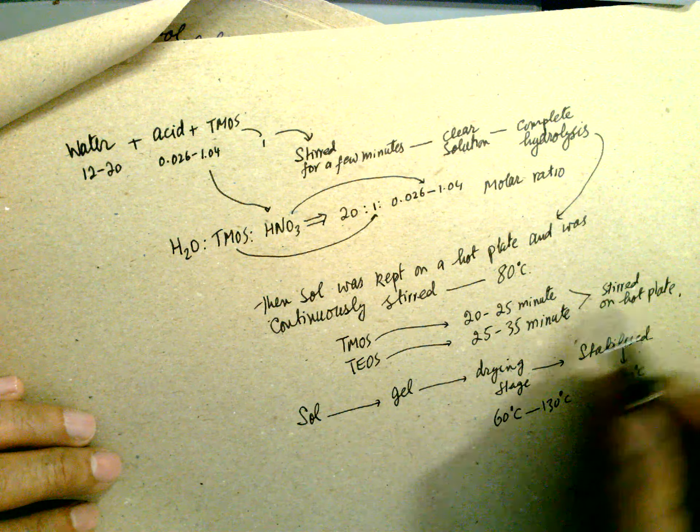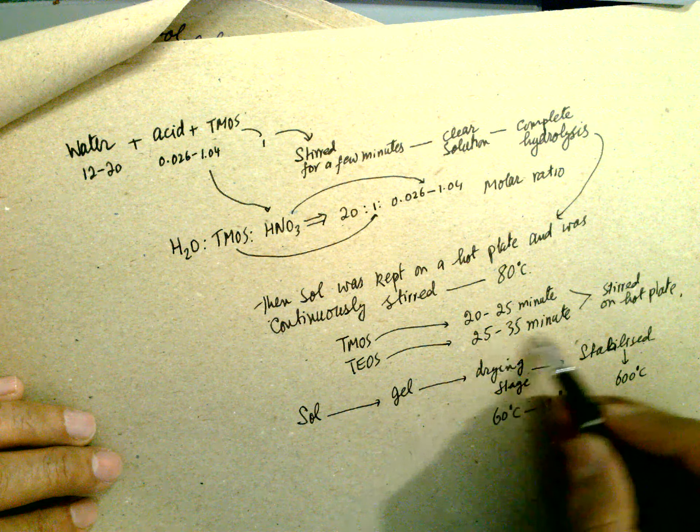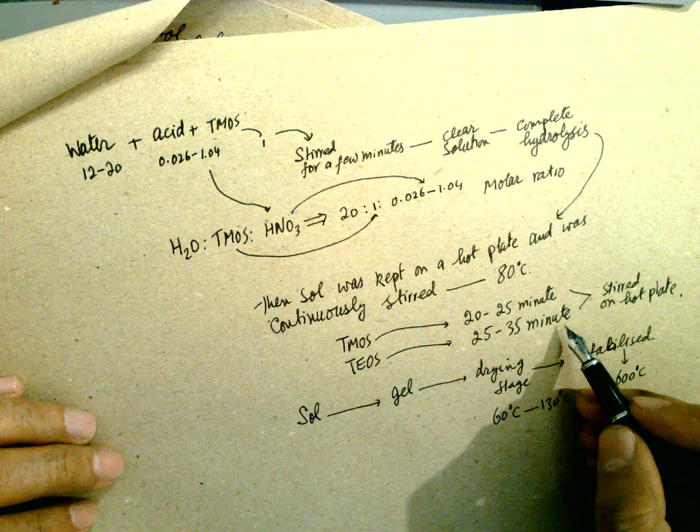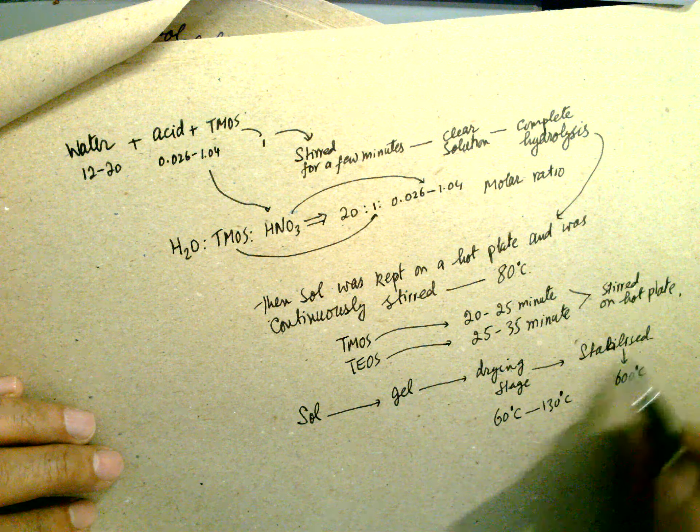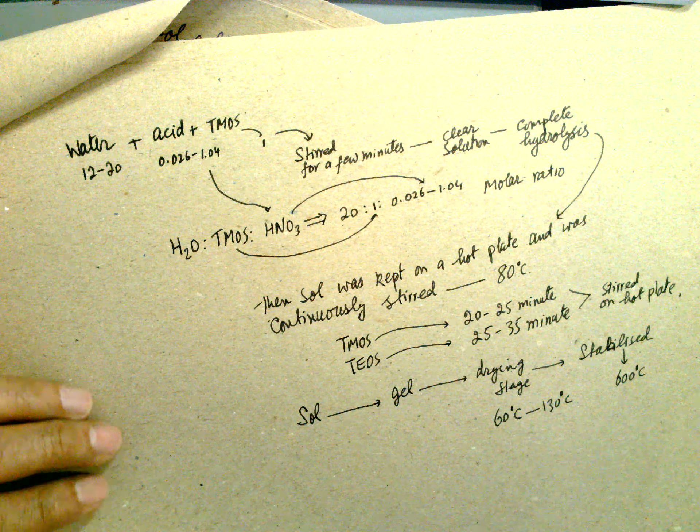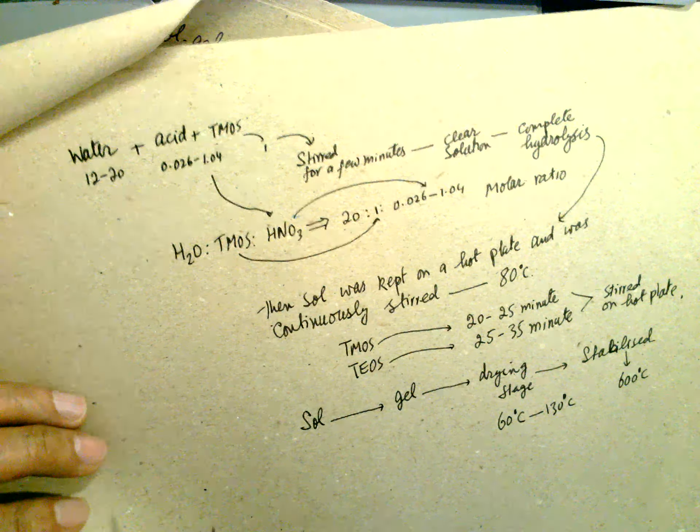Was continuously stirred at 80 degrees C. If you use TMOS, 20 to 25 minutes. If TEOS, it takes longer times for complete hydrolysis process. The sol, and then gel, and then dry, and then stabilized.